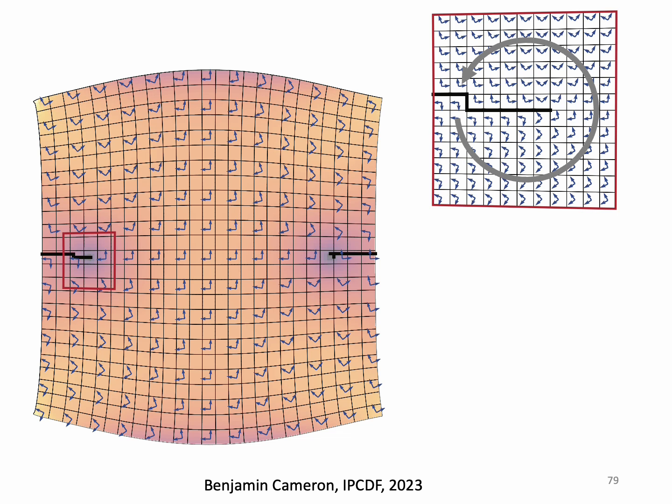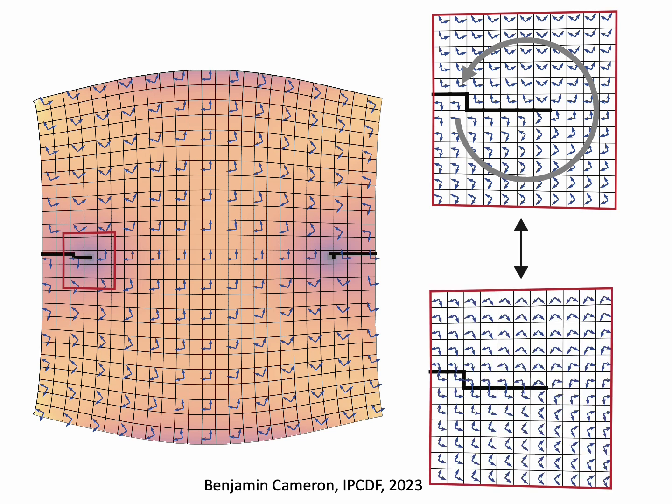So we're going to use the idea of going around twice and facing in the same direction and introducing another domain here, which you solve the equations in also. So we're going to say that this element is next door neighbors to this element. So it has a bunch of consistently defined next door neighbors. All the elements are happy. Then you traverse around here, everything's smoothly and consistently defined. And then this element will be next door neighbors to this element. So we're kind of solving the equations twice, and every element has consistently defined next door neighbors. And we have developed a computational procedure that will do this automatically for any problem.